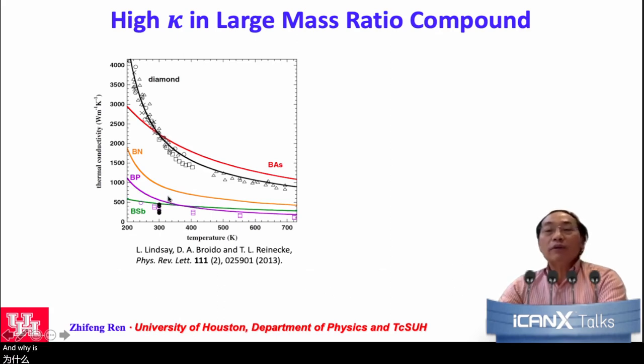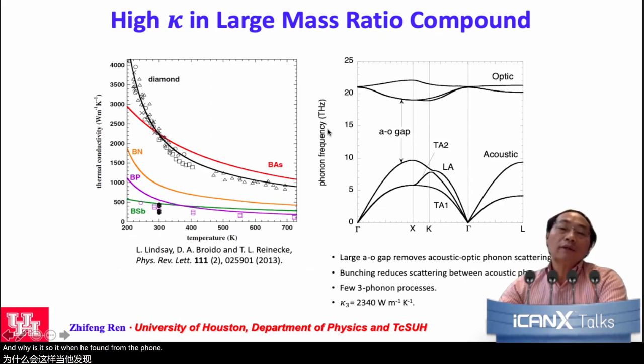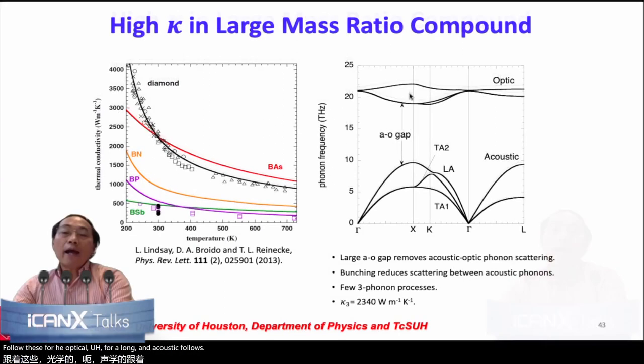And why is it so? When he looked at the phonon dispersion, he found that boron arsenide has a very interesting phonon dispersion: the optical phonons and the acoustic phonons have a very large gap here. The acoustic phonons also bunch together, a bunching effect, and two acoustic phonons' energy cannot reach the optical. So that's why they reduce the phonon scattering drastically. Because of that, they have this high thermal conductivity. And this is a theoretical prediction, no really experimental work.